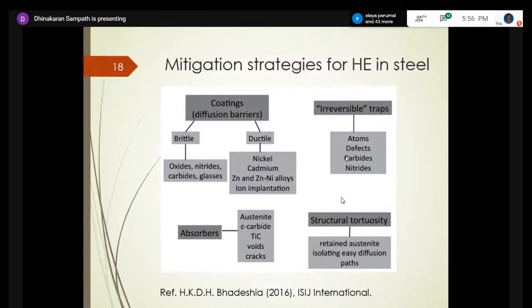The reason is that hydrogen freely moving in the matrix is what creates the cracking problem. Sometimes these traps also become a problem. But for one-time exposures to hydrogen, such as welding or electroplating, these will absorb the hydrogen, and then the material will function as usual. There are other similar irreversible traps, absorbers, which are all strong traps. They just absorb hydrogen and never release it, only at very high temperature.